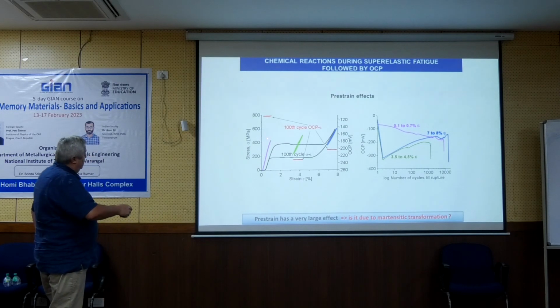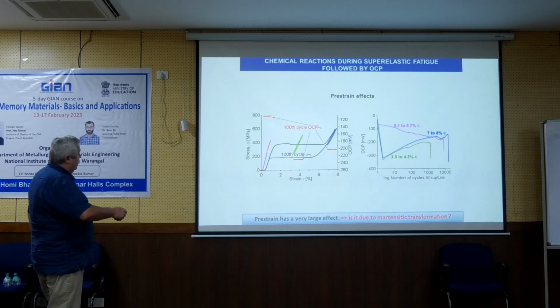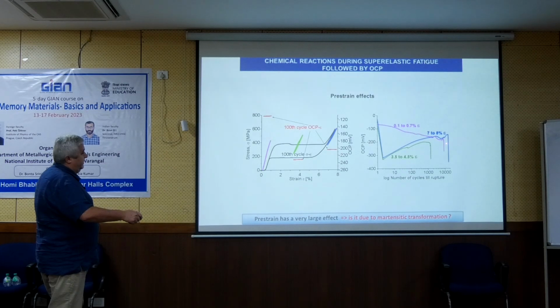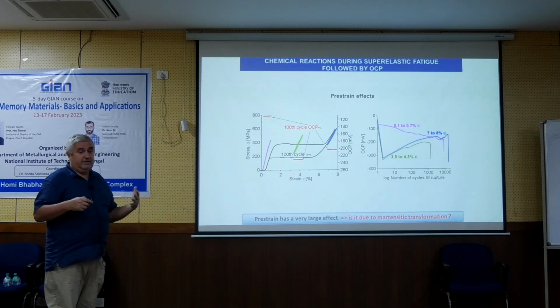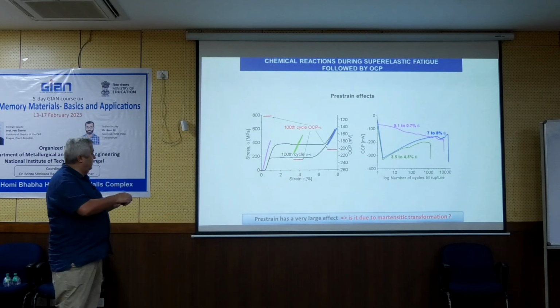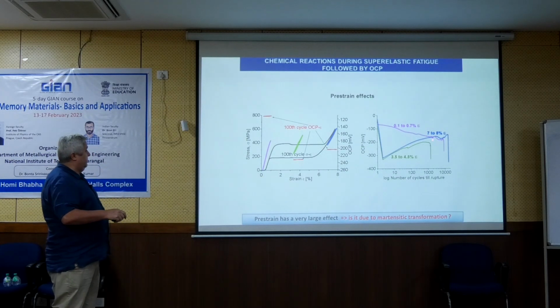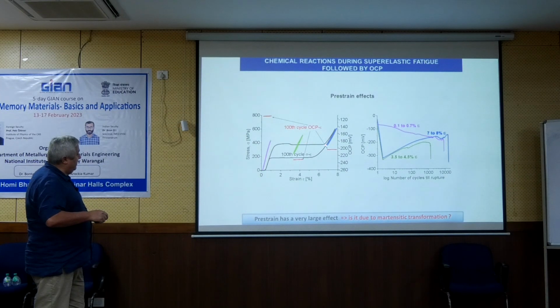So you see here, if we cycled between 0 and 400 megapascal, but in elastic range only, the OCP slowly degraded up to something like 10,000 cycles. Because in this experiment there were no cracks, it never cracked. But as you cycle in this range between 0 and 400, somehow probably the surface degraded, and because of that you have this decrease of OCP. If we did the same, but cycle in martensite, so there is a constant stress like 500 megapascal, and we cycle plus minus 50 megapascal something, the response of the sample is elastic.